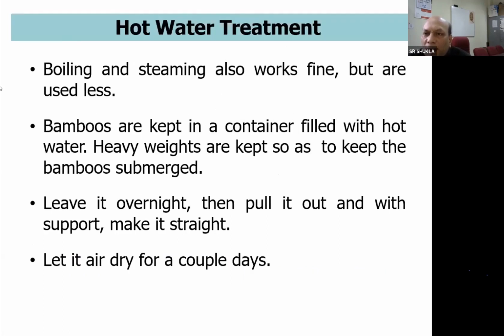This is hot water treatment. If suppose fire or torch is not available, then we have to use steaming and boiling the bamboo. This is less used, not much being used, because it is slightly expensive also, but it can be used. Bamboo are kept in a container filled with the hot water, and then we have to keep the bamboo overnight at least, submerged in these tanks, and then next day it can be taken out and it can be straightened to the required shape, and then it should be allowed to air dry for a couple of days.